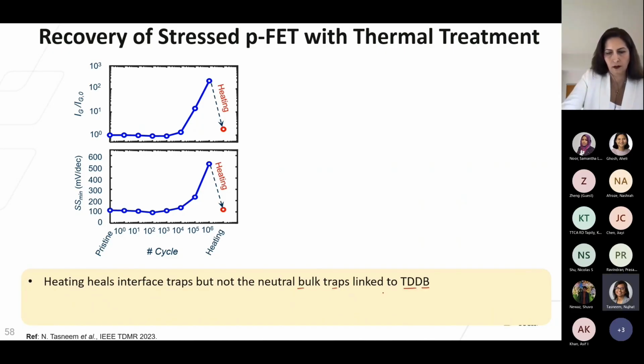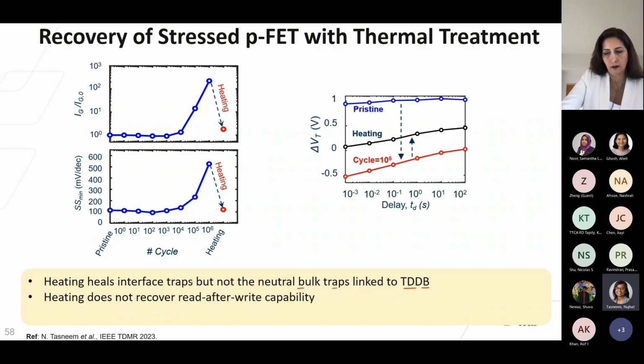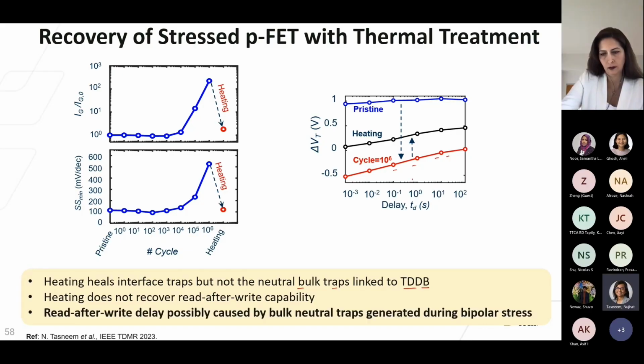And our results from this experiment also show that heating cannot recover the stress-induced read after write delay in PFETs. So these results strongly suggest that the stress-induced read after write delay in PFET is possibly caused by the bulk neutral traps that are generated during bipolar stress and that lead to breakdown. So these results were published in IEEE TDMR in 2023.